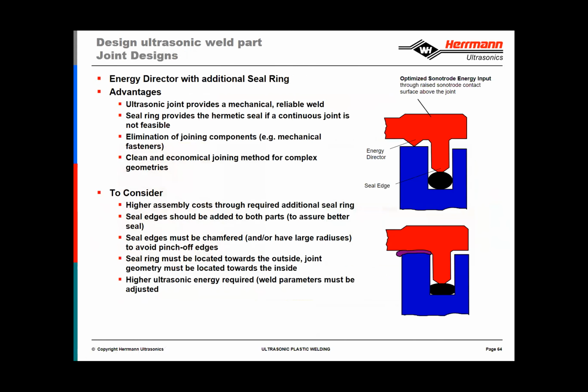There are cases where the ultrasonic welding can be used only for mechanical attachment of the parts, and an additional seal ring, O-ring, valve, whatever it might be, is what provides the actual seal. So in these cases, higher forces are typically required, but again, the bond is intended to only hold the parts together, and then the seal is created by that O-ring or that valve.